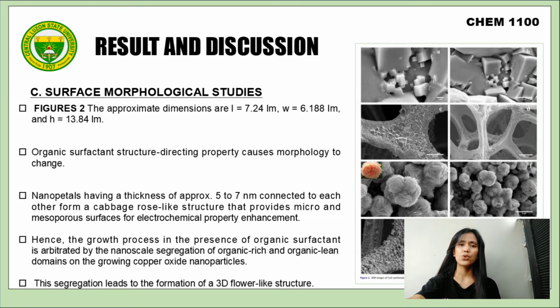The organic surfactant's structure-directing property causes the morphology to change. Surfactant provides a different degree of aggregation and grain size, leading to a different micro-nanostructure. Nanopetals having a thickness of approximately 5 to 7 nanometers connected to each other form a cabbage rose-like structure that provides micro and nano porous surfaces for electrochemical property enhancement.